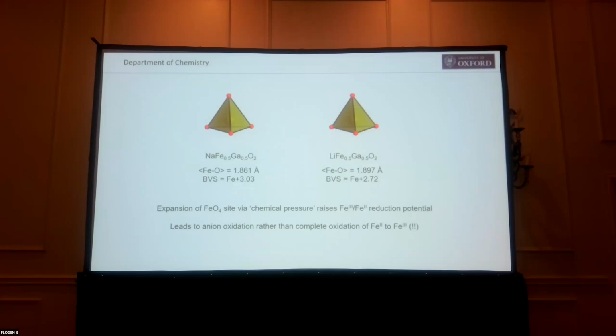But when we replace sodium with the much smaller lithium, the structure contracts. So we basically make all the iron-oxygen bonds longer, which lowers the bond valence sum. What it's really saying is that this site is now becoming much more suitable for iron. So it's changing the redox potential of that site, making it much harder to oxidize. And that pushes the iron 3 to iron 2 potential to a position where it then starts to compete with the anion redox.